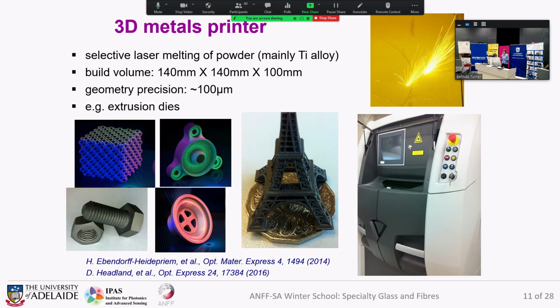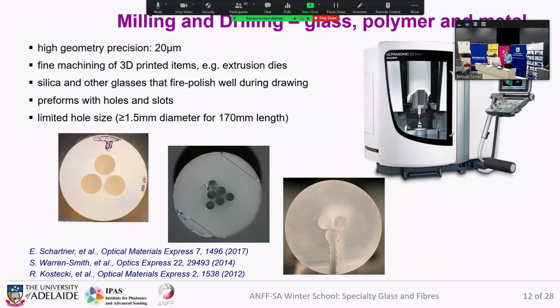Our 3D metal printer works with the principle of selective laser melting of powder. We use mainly a titanium alloy. The geometrical precision is 100 micrometer, that means 0.1 millimeter. That brings me to my next slide. The 0.1 millimeter, of course, precision is not enough if you want to make an extrusion die where we have slots of 0.3 millimeter.